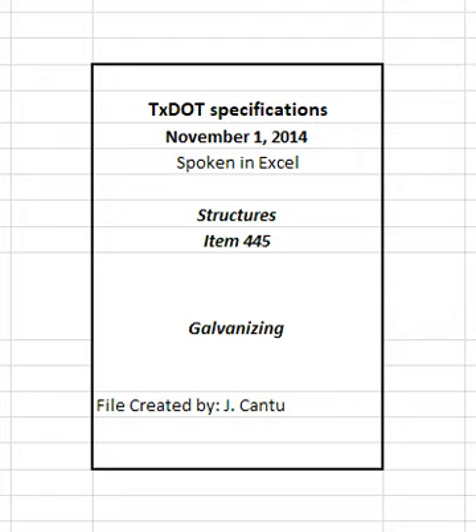Ensure cleaning and galvanizing does not produce hydrogen embrittlement. Remove weld flux, weld slag, and any other weld residue or impurities before galvanizing. Before galvanizing material 1/4 inch or greater in thickness, remove all sharp burrs, and chamfer to approximately 1/16 inch all edges.